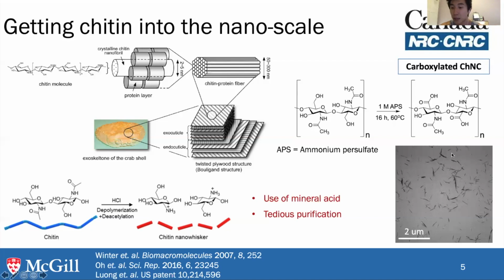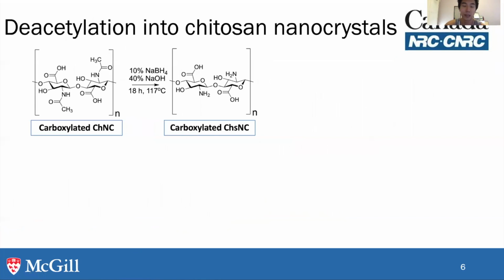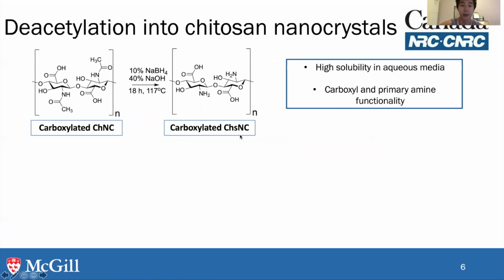And you can see here, similar to cellulose, it has similar size domains, around 200 nanometers in length, and a high aspect ratio. Now, what we really want to do, however, is go from chitin nanocrystals to chitosan nanocrystals. Similar to the bulk version, we want the chitosan nanocrystal with the amine functionality because it is highly soluble in aqueous media, as well as having the carboxyl and amine functionality handles,